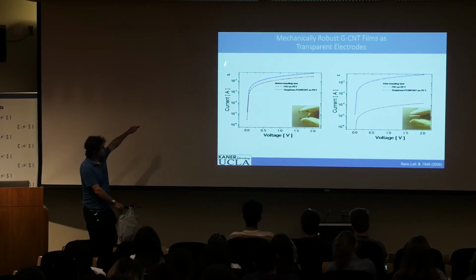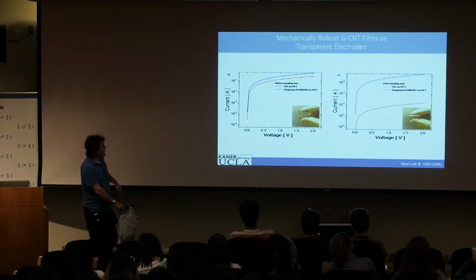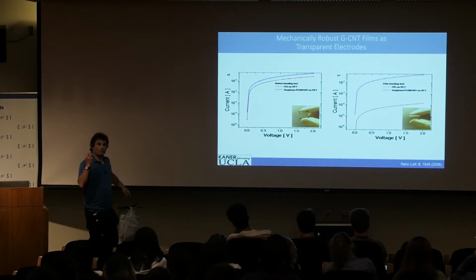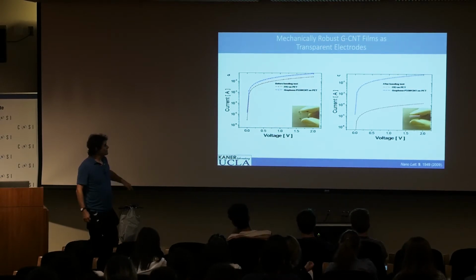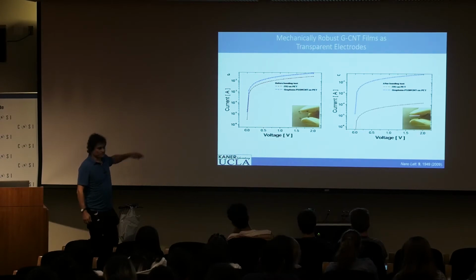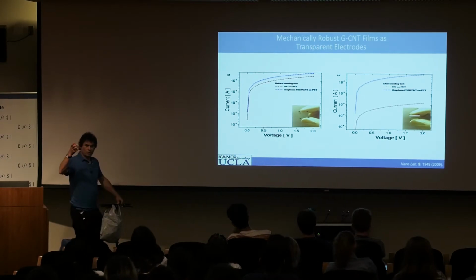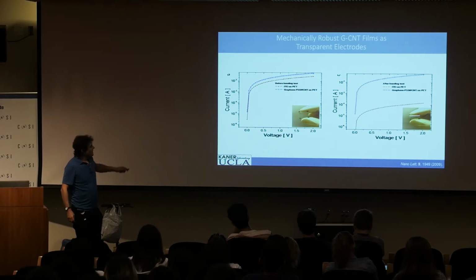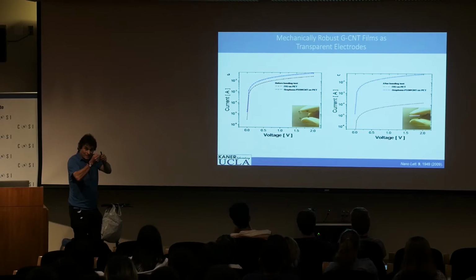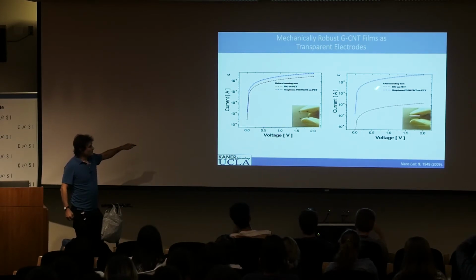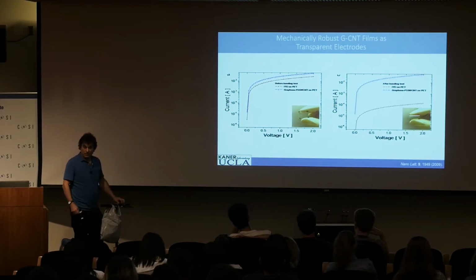So here's indium tin oxide. This is a current voltage curve. And what I'm showing here is we put some of our graphene with carbon nanotubes onto plastic. PET is polyethylene terephthalate. That's what your Coke bottle or water bottle is made out of. And here's indium tin oxide. That's what's used on your cell phone. And then we put it on plastic and we bent each of them 10 times. And when we did that, you'll notice that the indium tin oxide drops by 3 orders of magnitude in conductivity. But the graphene carbon nanotube combination doesn't have any change. So basically, we have a flexible, transparent conductor.